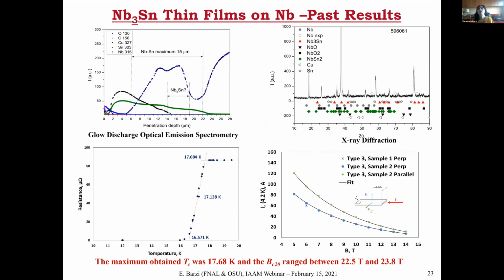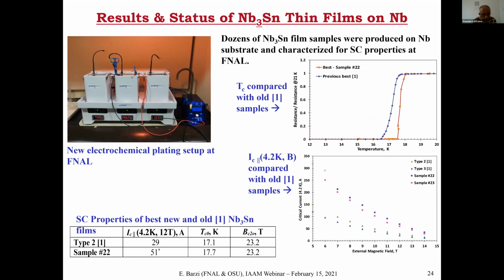So these are diagnostic tests that were done on these films by the Politecnico di Milano, like glow discharge optical emission and X-ray diffraction, and this showed the presence of niobium-tin after heat treatment on these films. And here I'm showing our tests at Fermilab of the critical temperature that is measured by measuring the resistance of the film as a function of temperature. When you see the transition from zero resistance to a finite resistance, you have your transition to superconductivity, and you can define your critical temperature. And here I was even measuring the transport current in these films. Anyway, this was just to give you an idea of side products that were obtained through the research on niobium-tin.